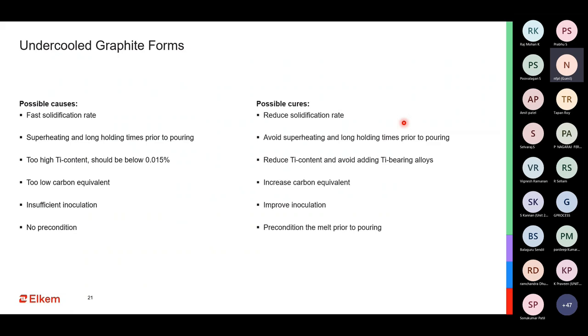How do you solve it? By reducing the solidification rate. It depends on the type of casting. It is not always possible, especially when you're making thin section castings. But there can be some ways of doing it, like slowing down the rate of solidification. Two, we need to avoid excessive superheat and holding times. We have to control titanium and other such elements which are deleterious to graphitization. We have to improve preconditioning and inoculation, and also choose a suitable carbon equivalent for the kind of casting that we are manufacturing.